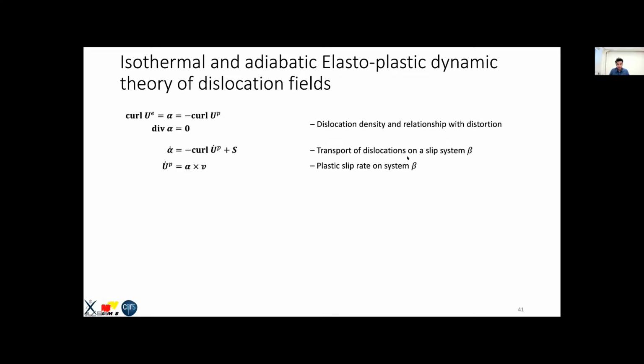The next equation is the transport of dislocations. For a slip system beta, you have alpha dot equal to minus curl of u dot p, and u dot p is alpha cross v. This is the plastic slip rate, which has a relationship with the Orowan law. The velocity of the dislocation is prescribed constitutively from a dissipative relationship, so you have to respect this relationship, and essentially any expression for v that respects it is admissible.